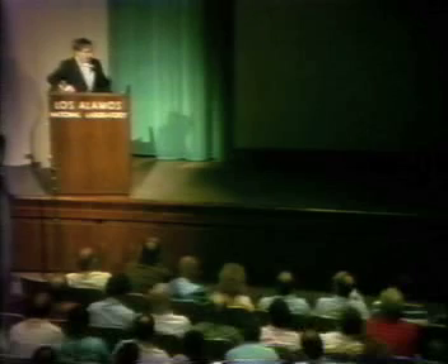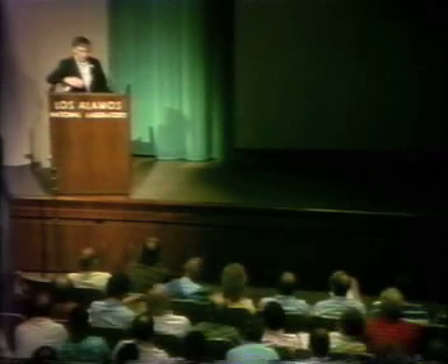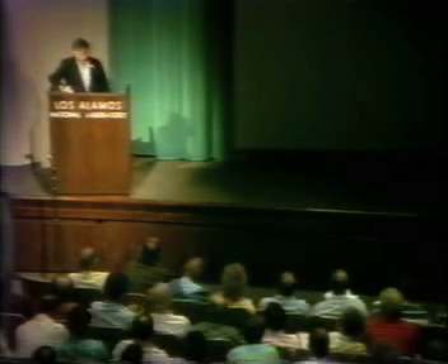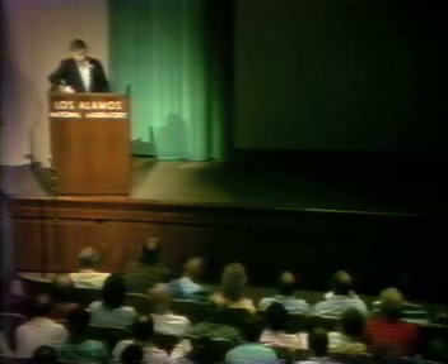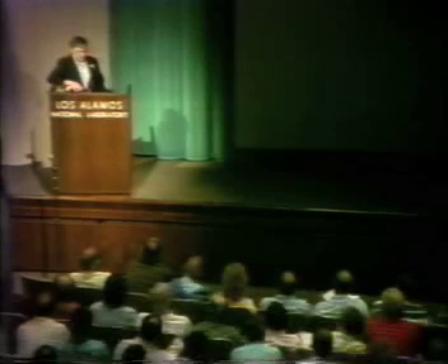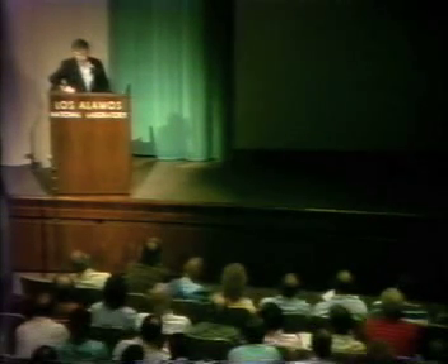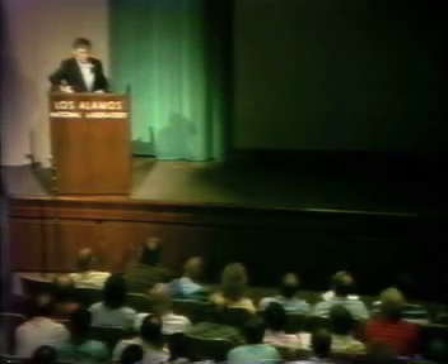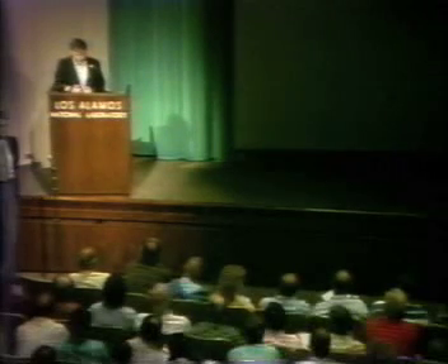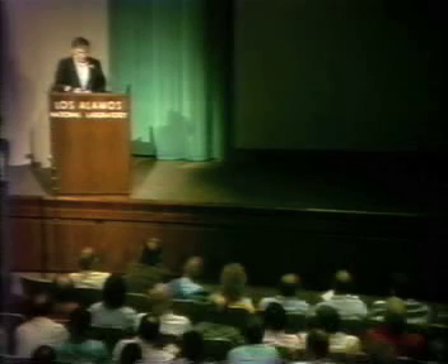Can you describe how long after the initiation of the experiment you first see excess heat, and then subsequently how long does it take the excess heat to reach equilibrium? All of the experiments, up to a 4 millimeter rod, are at equilibrium by 250 hours after we start. There is the expected rise in temperature that you would expect from just Joule heating in the cell over about several hours after you start the experiment. And then for an electrode that takes, say, 3 weeks to charge up, you will see not too much of a change over the next week and a half, and then in the last week you will start to see the temperature rise up to the 6.5 degrees that you saw here. So that temperature cycle takes about a week. We usually wait about 5 times the diffusional relaxation time before we think the thing is at total equilibrium.